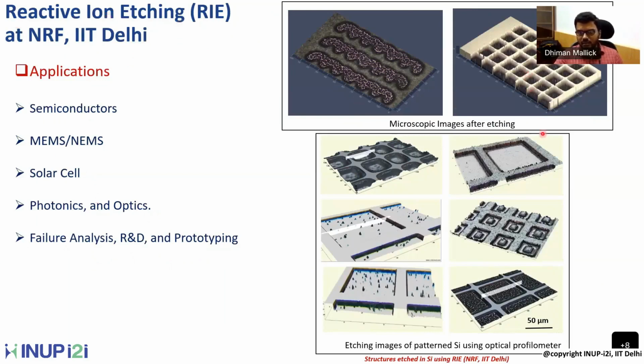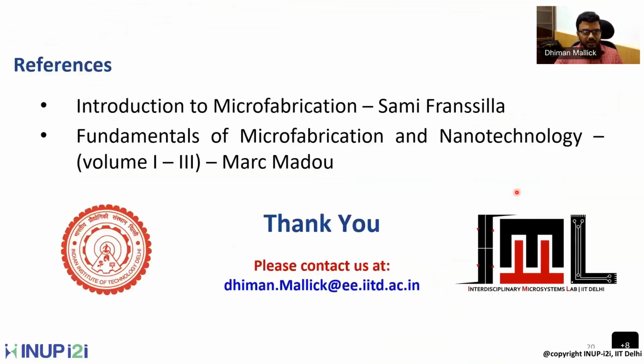So these are some of the etching profiles in silicon that have been done recently here. The etching profiles are shown here. By optimizing the different etching parameters, our students have been able to etch up to a very large depth, almost 80 to 100 micron, and the side profiles are also not that bad. They are quite anisotropic in nature. But obviously these processes can be further optimized according to the requirement. That is a different thing. But this is the facility that we have right now. So I hope that you get a flavor of different etching processes, particularly this reactive ion etching process.